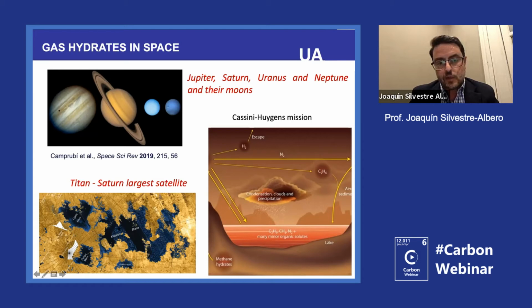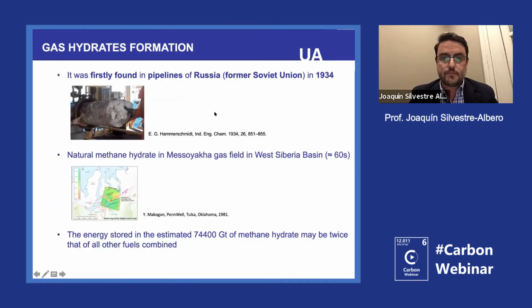And what they observed is that all these lakes that you have on Titan are made of liquid. So it's the only moon where you have liquid like on the Earth. But this liquid is not water. This liquid is made of hydrocarbons, so mainly methane, ethane, and also organic solutes. And the predictions say that those are the perfect conditions to have methane hydrates at the bottom of these oceans. So that means that gas hydrates in general are a very general way to store, as I say, methane in the environment, not only in the air, but also in other planets and moons.